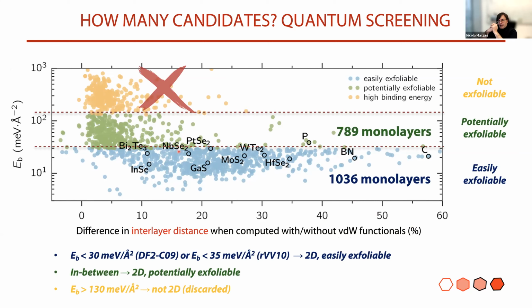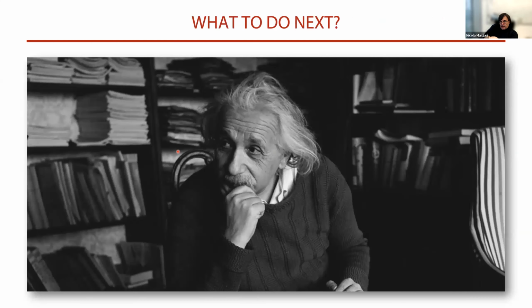Then we have some green materials that might be exfoliable, a bit tougher. And then we have a lot of materials that are layered, but with a really very large binding energy because typically they are intercalated with cations and anions. So it's almost ionic in character, and you can't break them apart easily. But the net result is that all of a sudden we don't have one 2D material or 20, but we have 1,000. And right now we have actually kept going on this project, so we have 2,000 exfoliable materials. And the question is what to do with this.